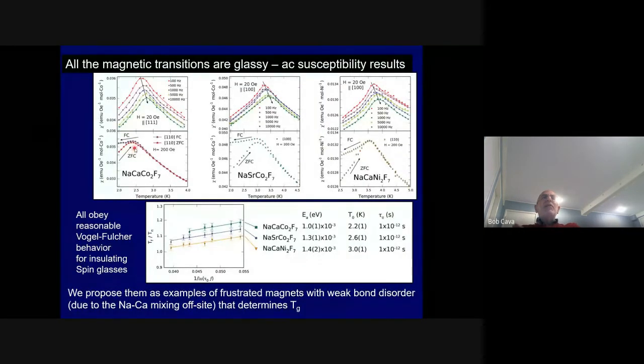And there are classic experimental signatures for spin glasses. And so I think that these materials would be like the world's most perfectly frustrated magnets if we could figure out some way to get rid of this disorder. And the materials physicists who we work with have been bugging me for like 10 years now to figure out how the heck to do that. I can't imagine how to do it because I need this site to add to 3, or I need to put some oxygen on the fluorine sites here, or do something to make this go away, but I can't make it go away. Anyway, they're spin glasses.